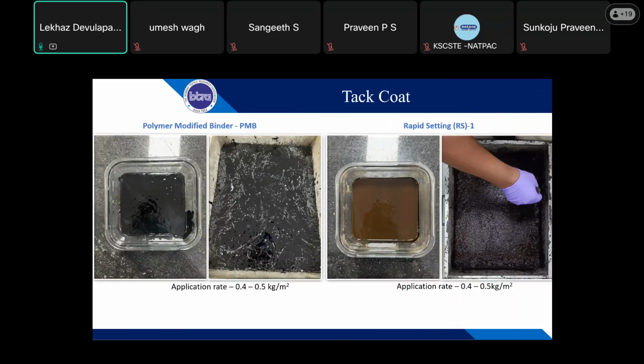And then we come to the tack coats. We have chosen two tack coats. One is the rapid setting one tack coat that we usually use, which has a residue content of some 60 percent bitumen residue. And then we used a polymer modified binder. It's not our PMB; it's a different kind of polymer modified tack coat, which has a high softening point of up to 110 degrees. And then we fixed a rate of 0.4 to 0.5 kg per meter square. How we fixed it, I will get back to in the tests conducted.